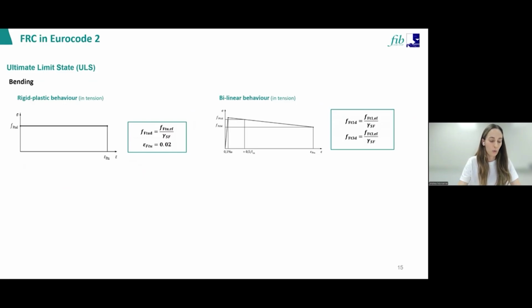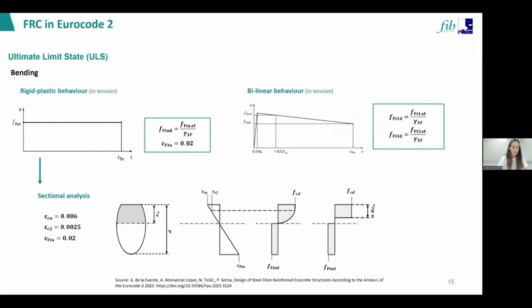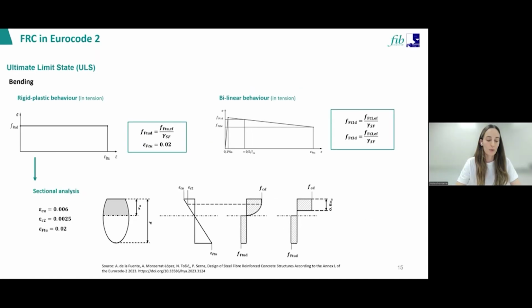Let's see the most important ones. So, for example, for bending, at the ultimate limit state, Annex L proposes simplified constitutive models to represent the residual tensile behavior. Two approaches are considered: a rigid plastic behavior or a bilinear behavior in tension. In practice, the contribution of fibers is introduced in the sectional analysis through residual tensile stresses acting below the neutral axis after cracking. And in compression, the same stress block approaches used for reinforced concrete may still be considered, although modifying the compressive strength parameters to account for the increase of ductility that fibers give to the concrete.